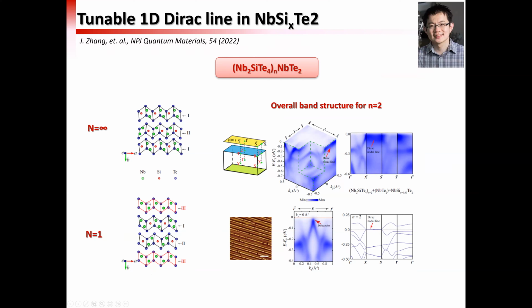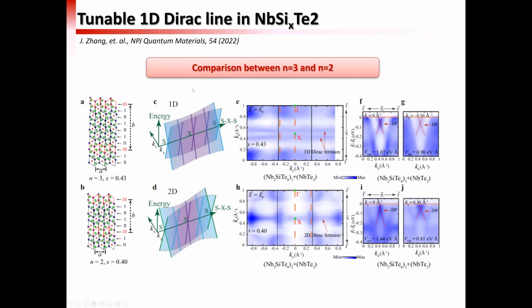So we basically will just want to vary this n, adding more insulating layers between the conductive niobium tellurium 2 chains. When n increases, the conducting layers, the chains, are further apart, so it is more one-dimensional; otherwise it's more two-dimensional. Going to the comparison slide, you can see that for chains further apart, the one-dimensionality is better.